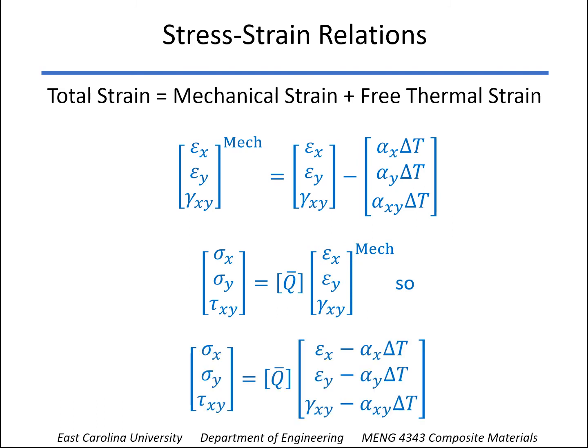So we can write it as shown on the bottom line here once we put in the stress-strain relations, that the stresses are equal to the Q-bar matrix times the strains, and again, just the mechanical strains, so the total strains minus the free thermal strains.